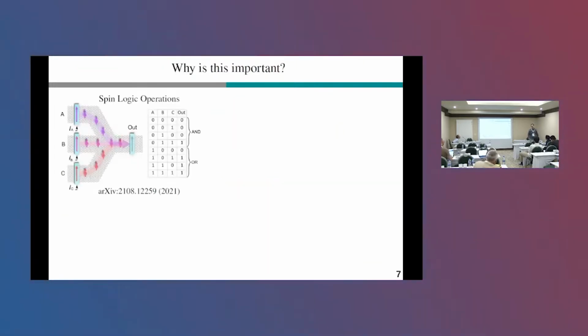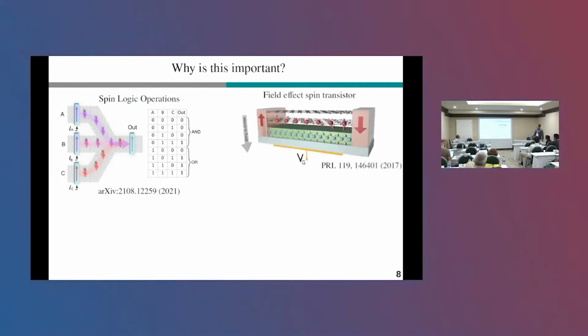Now the question is, why is this important? I think today we have already seen why graphene physics is important. Graphene has very nice spin and charge transport properties, and it can be used to perform spin logic operations. On top of that, when you combine graphene with a TMDC, it can be used as a field effect spin transistor. In this particular case, it's bilayer graphene on top of tungsten diselenide or another TMDC. It does not matter really much. What is important here is the short-rangeness of the proximity effect. So only the lower layer is proximitized. And on top of that, with the electric field, we can then switch the band structure. So we can effectively turn on and off spin-orbit coupling in the transport channel. And this can be used as a field effect spin transistor.